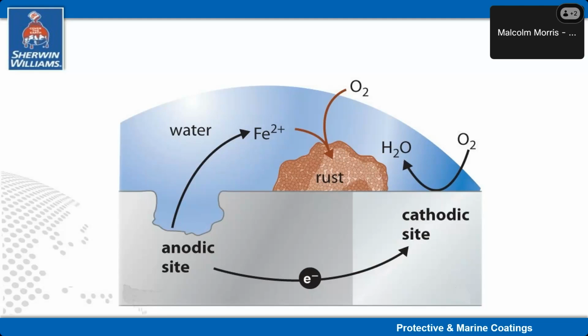Oxygen is the important fifth element to the cell, if you like. Without oxygen, corrosion will not happen. The best analogy for this is if you think of the shipwreck, the wreck of the Titanic. There's divers with cameras been down there. The wreck is still there after 100 odd years at the bottom of the Atlantic.